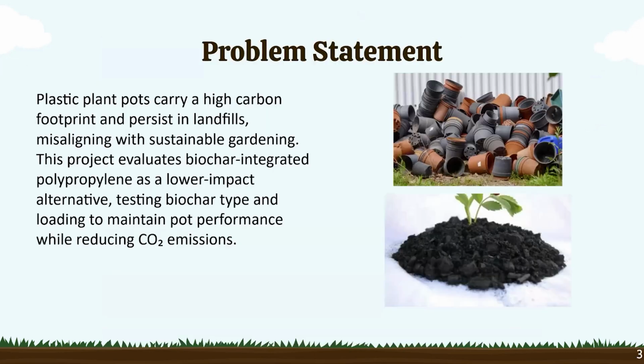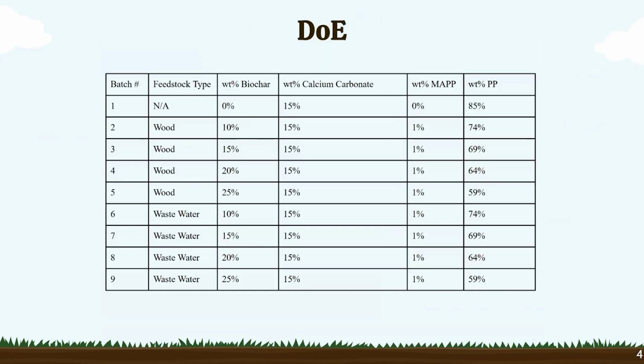The problem that we were presented with by our parent company, Sintrust, was to redesign the plant pot material so that it's able to have mechanical properties similar to that of polypropylene, but have significantly less carbon impact on the environment. And to do this, we were tasked with taking two different types of biochar and incorporating that into a plastic and biochar master batch, and then running tests with it.